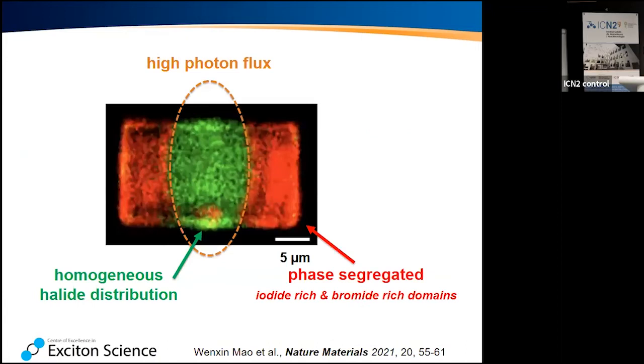And here's an image of a crystal, so one of these platelets. We have a low energy, or 10 watts per square centimeter, background illumination. And here in the center is where we're illuminating with a high intensity light. You can see that here in the center is where we cause the remixing, and in the boundaries you still have your segregated state. So that depends on the intensity of the light. Correct. Yeah.